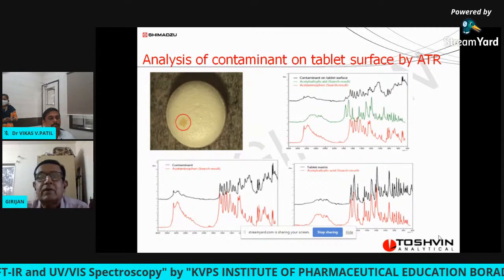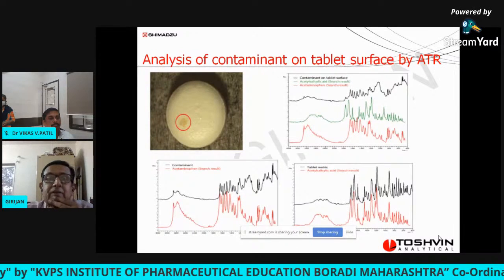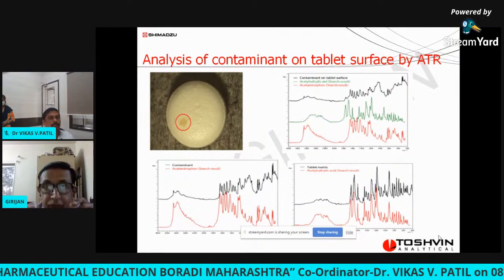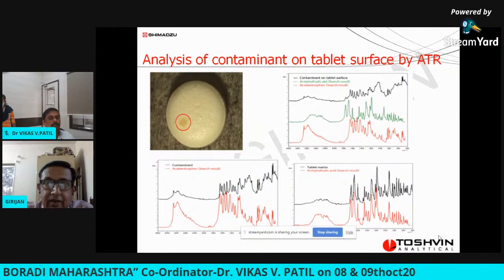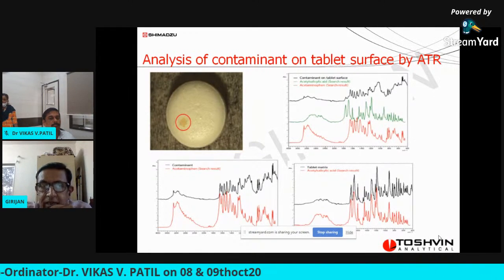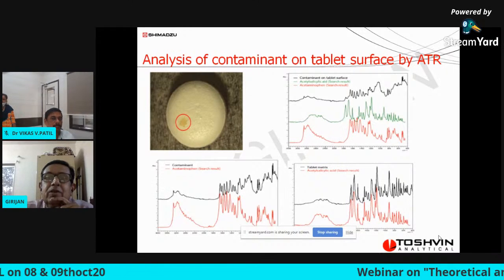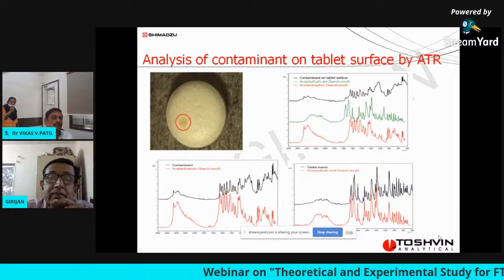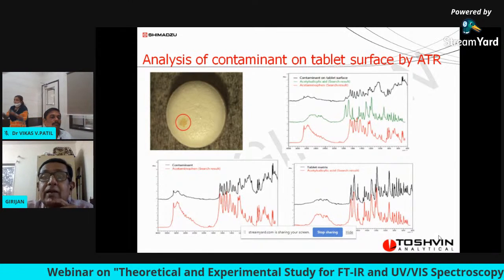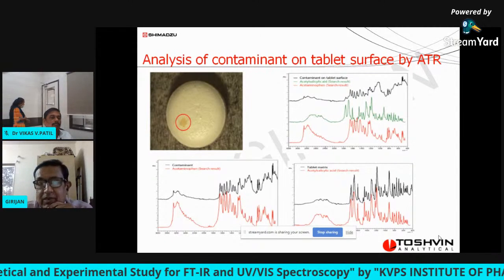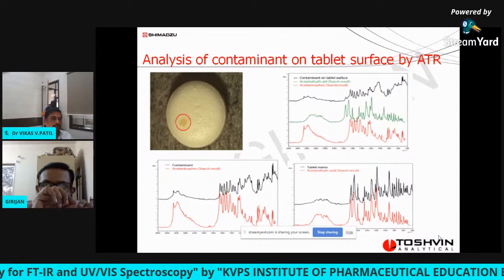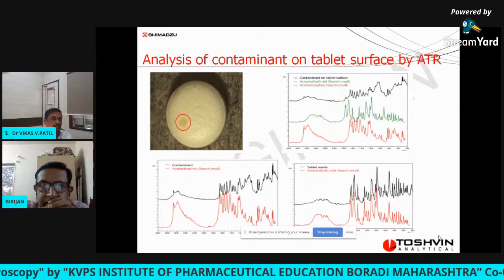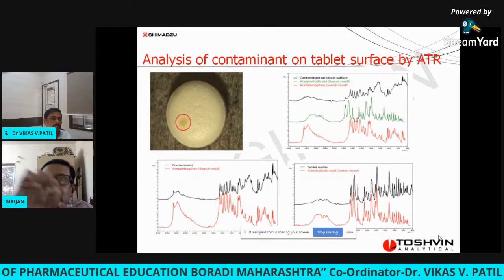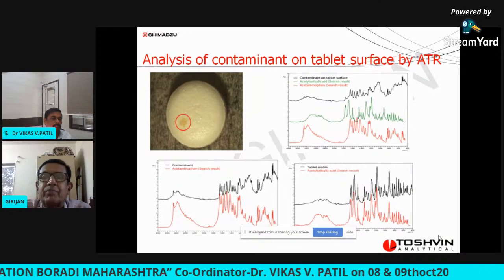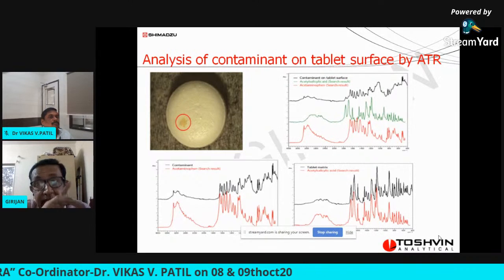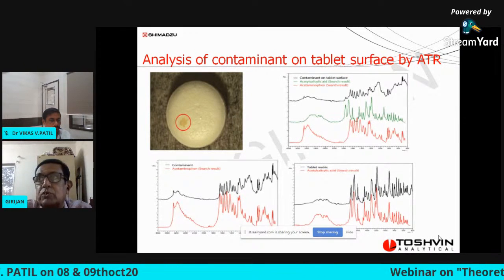So what we have done is we have taken the ATR spectrum. We have kept the tablet as it is on the ATR crystal, and then we record the spectrum of that particular area. So there are two possibilities. Look at the right-hand side spectrum, the top spectrum. The black color is the contaminant on tablet surface. We have kept that surface exactly on the ATR and recorded the spectrum of that area, and that gives a black colored IR spectrum. Now we have gone for a library search. The library search is giving us two possibilities.